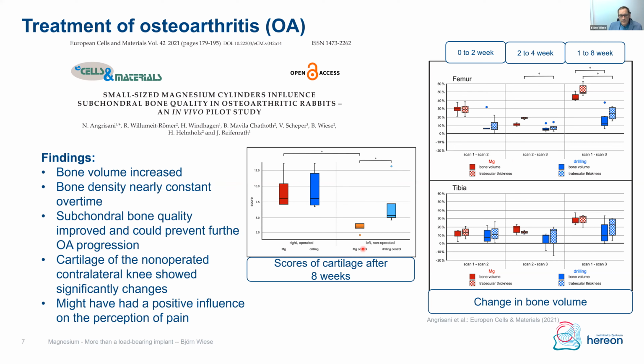What does it mean? Here's the score. It's the score for the quality of the cartilage, and if the number is small, it means it has a better quality of cartilage. And we see that the magnesium in the right knee will improve the quality of the cartilage in the non-operated knee. That means there's some effect. It might be, but we are not sure up to now, a positive effect of magnesium on the pain reception of these rabbits, and it makes it better to move, and in the long run it improves the quality of the cartilage in this knee.